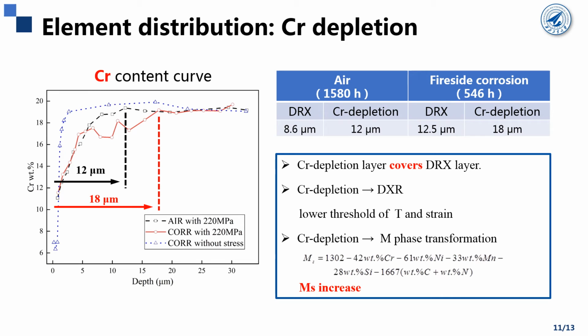Since the measured chromium depletion layer covers the layer for recrystallization, it is reasonable to consider that the occurrence of dynamic recrystallization is associated with chromium depletion. That is because the chromium loss in the surface layer helps to lower the threshold of the temperature and the strain for the occurrence of recrystallization.